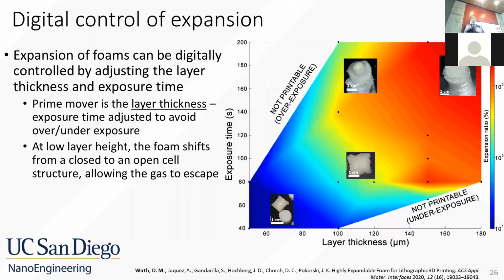This expansion can be controlled digitally. In other words, just by varying the exposure time and layer thickness of these 3D printed structures, we can control exactly how much they expand.